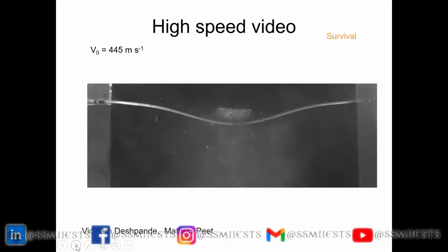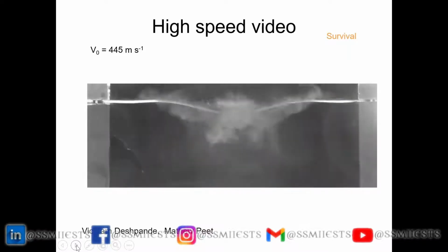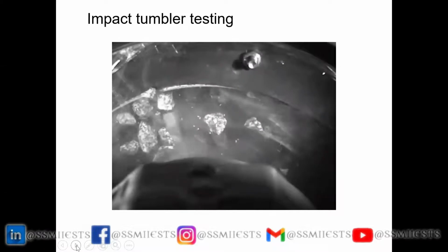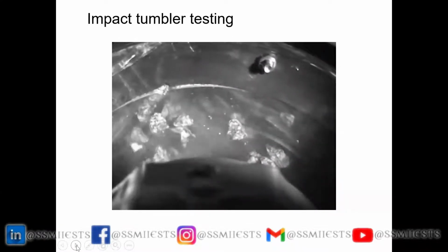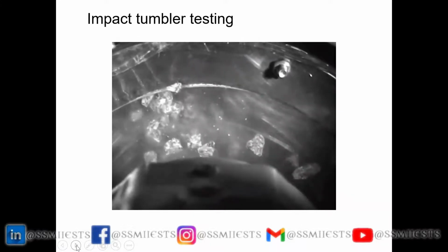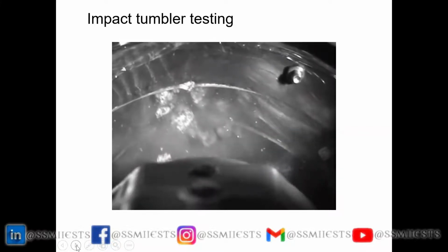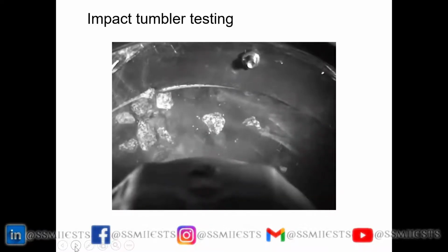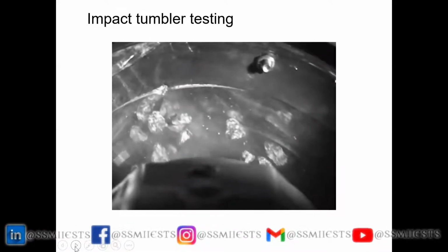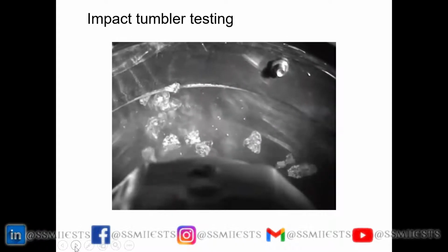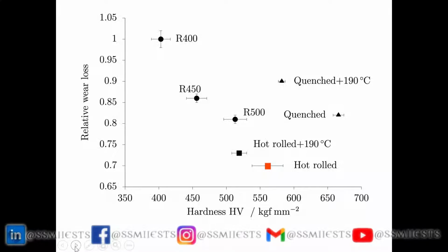But you really want to think of more than just defense applications. So if you go to the next slide, the next slide will show you a very severe wear test. The thing that's rotating around is steel samples which are hitting granite. And this is at a very high speed. This is a slowed down version of the movie. Basically, this is a very severe test where we get both impact and abrasion. And this material proves itself to be better than anything that is commercially available. If you go to the next slide. The red dot there is straight out of the rolling mill, okay? And you can see that it has outstanding wear resistance compared with anything else that is available.